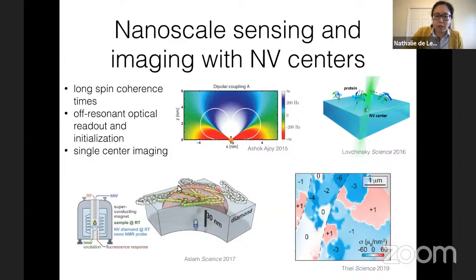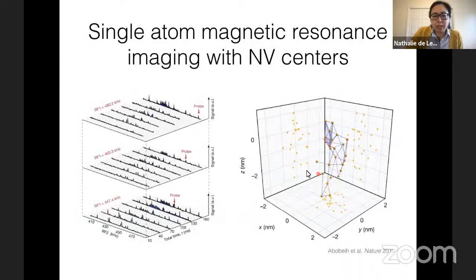People have used this to look at ensembles within a very small volume right on the diamond surface. And there's an enormous amount of work using this for things like condensed matter sensing, where you can map magnetic fields and magnetic textures in some nearby material system. Pushing this to really incredible single atom scales, people have also started doing something that looks a lot like magnetic resonance imaging, but at the single atom or single molecule level. The idea is that you can think of this NV center as having the largest possible magnetic field gradient for MRI, because you really have this point sensor, and that enables you to get extremely high resolution. So this is a beautiful example out of Tim Taminiau's group from a couple years ago, where they took an NV center and used it to resolve the positions of individual carbon-13 nuclei in the diamond lattice.